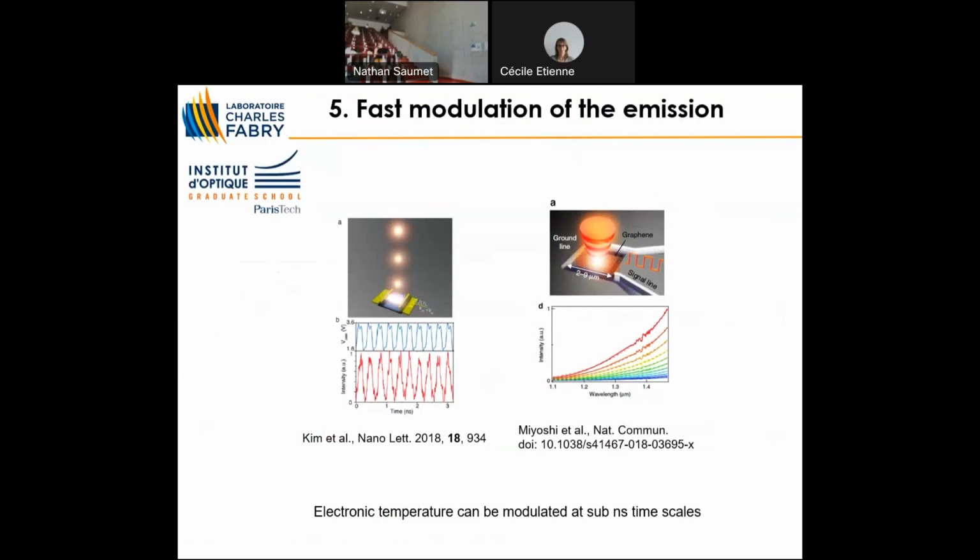And the signal is here, and you see the time. This is absolutely amazing. That's 1 nanosecond. So here the period of the modulation is 300 picoseconds. So how is it possible that it cools down? Once you stop heating the electrons, they cool down by electron-phonon interaction. The time it takes for electron-phonon interaction is 1-2 picoseconds. And the heat capacity of the phonons is immensely larger than the heat capacity of the electrons. So the lattice doesn't heat up.